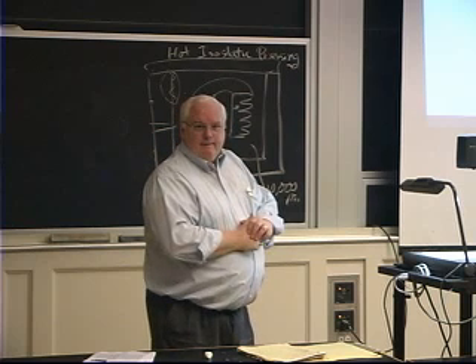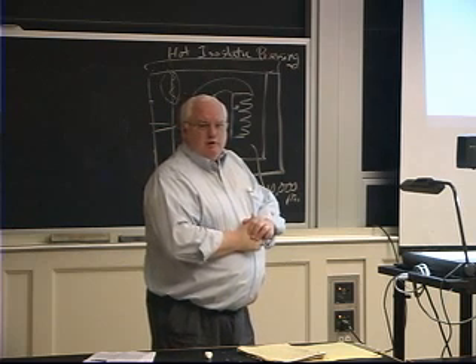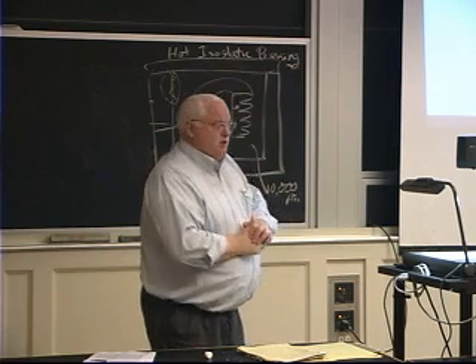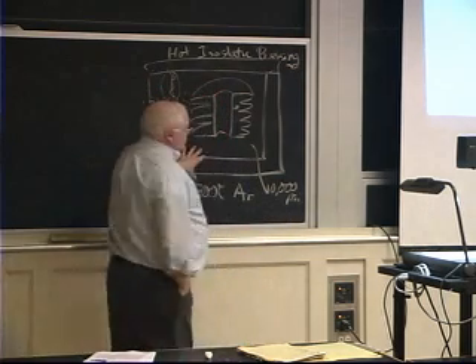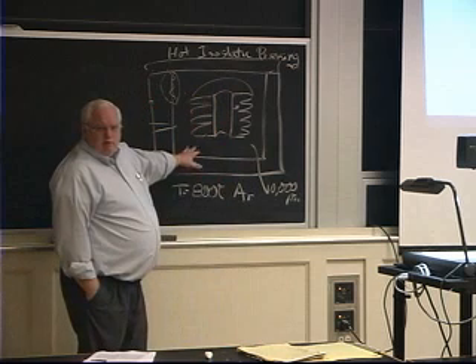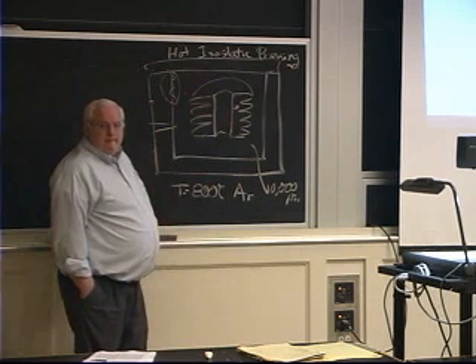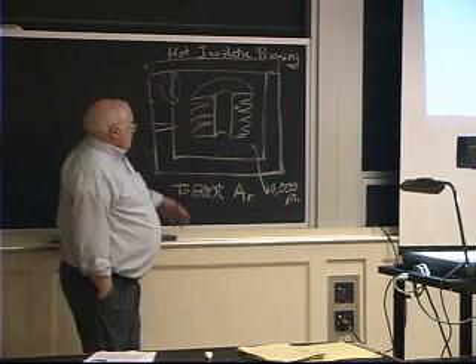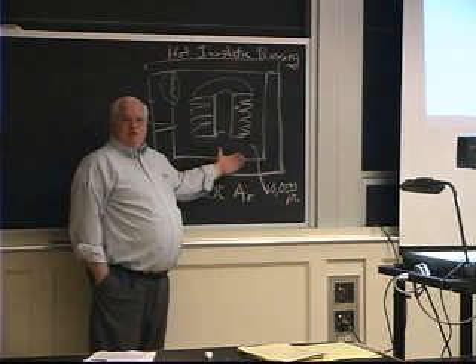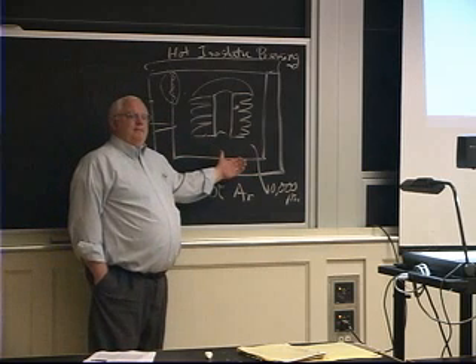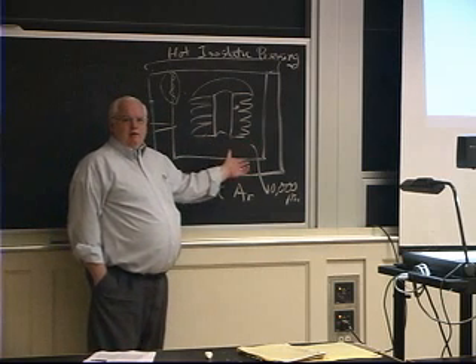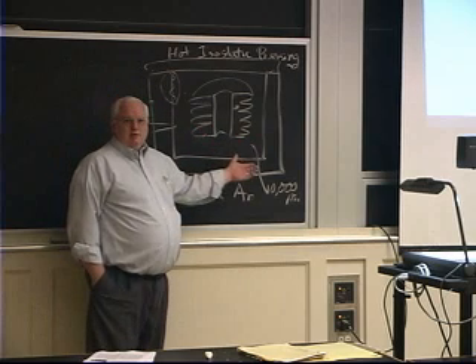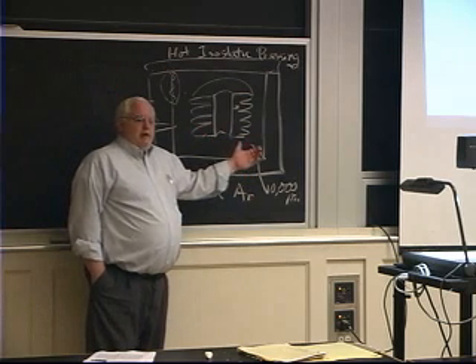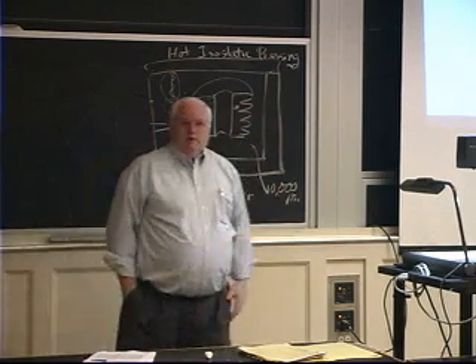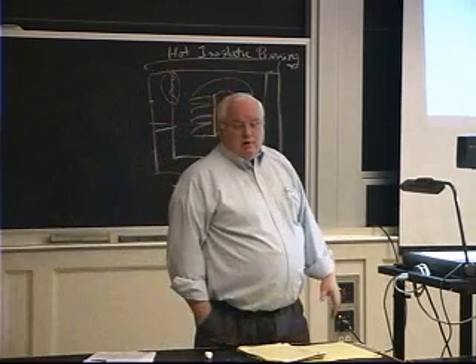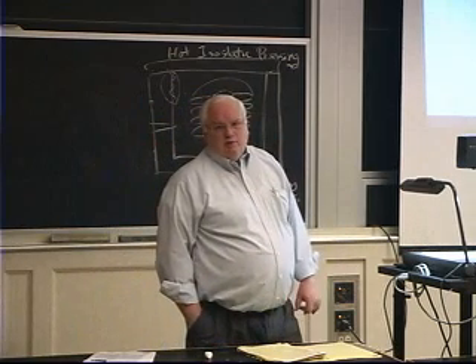How old was that vessel before it blew? It was about 12 or 13 years old. Built in the mid-80s, and this all occurred in the 97, 98 time frame. What's a typical lifetime, like 50 years? Well, no one could ever say, this was the first one of this size. Typically, you talk numbers of cycles, and the number of cycles might be 20 or 30,000 cycles, heat treat cycles. And so if you're doing 200 a year, 10,000 cycles, yeah, you can get a 50-year life if they design it for 10,000 cycles.